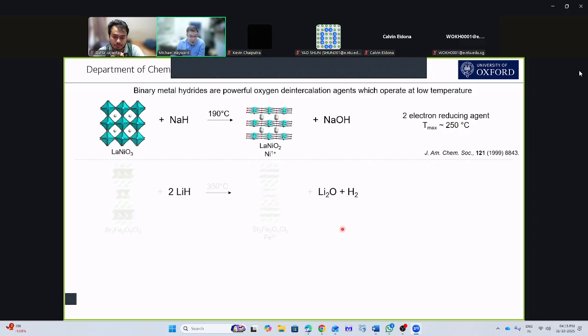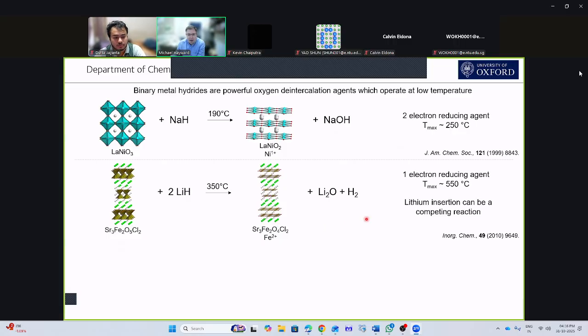Alternatively, though, we can use lithium hydride. So lithium hydride is a 1-electron reducing agent. It extracts oxygen to make lithium oxide and hydrogen gas, so H- to H0. And here's an example of an iron 3 to square planar iron 2 compound. And now we can get the temperature a little bit higher. So now we can get to about 550 degrees C before lithium hydride becomes lithium and hydrogen. Although we need to watch out for the lithium insertion reactions that lithium hydride can do.